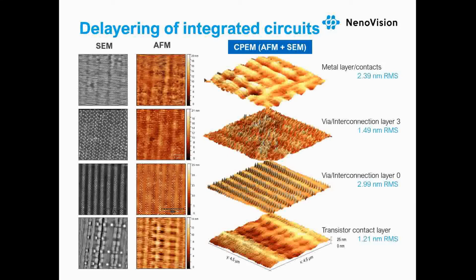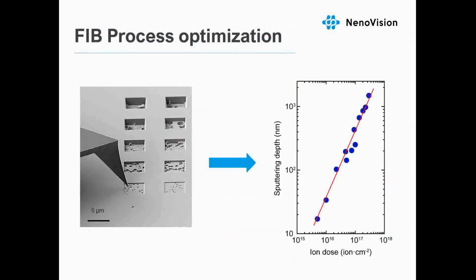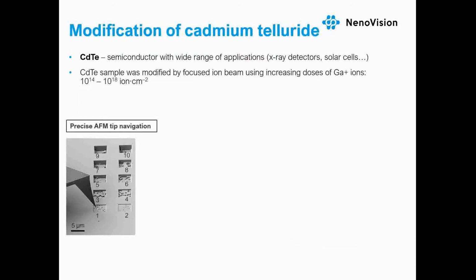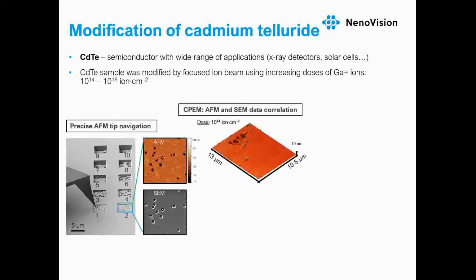This application demonstrates how the combination of AFM with SEM equipped with focused ion beam can be utilized to optimize the focused ion beam milling process. And for this purpose, cadmium telluride was sputtered using increasing doses of ions as depicted in the SEM image. Each of the 10 frames was immediately analyzed by AFM and SEM in in-situ conditions. The AFM and SEM data were correlated using CPEM technology and used to optimize the FIB milling process.